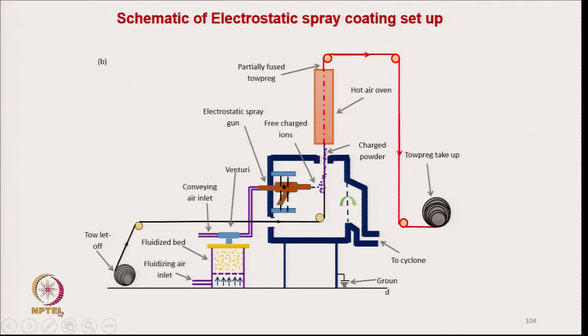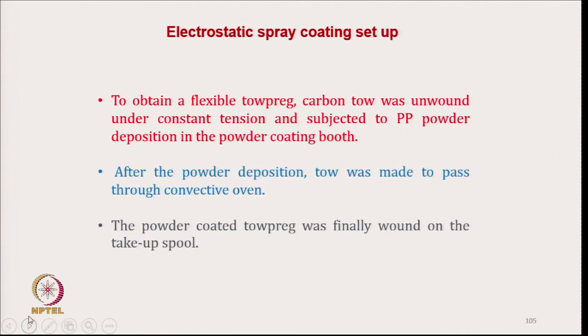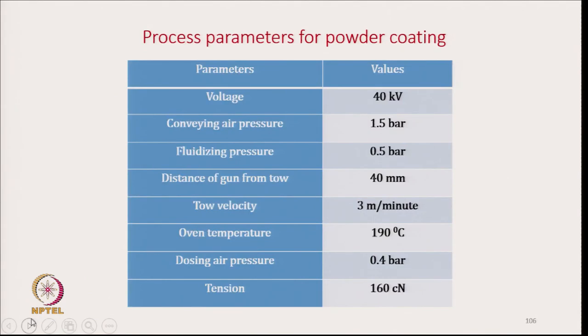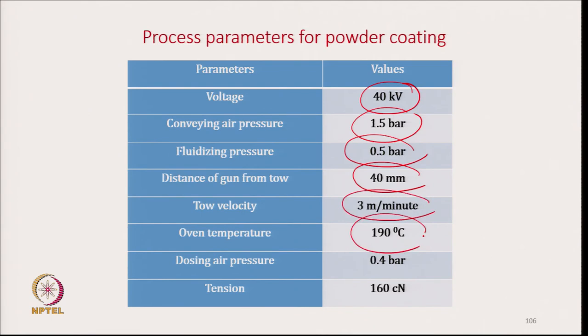This picture we have already explained in detail, the schematic of the spray coating, where we get the powder coated tow. So, these are the parameters which have been used in the powder coating. Voltage 40 kV, conveying air pressure 1.5 bar, fluidizing pressure 0.5 bar, distance of the gun from the tow 40 millimeter, tow velocity 3 meter per minute, oven temperature 190 to keep the flexibility intact.